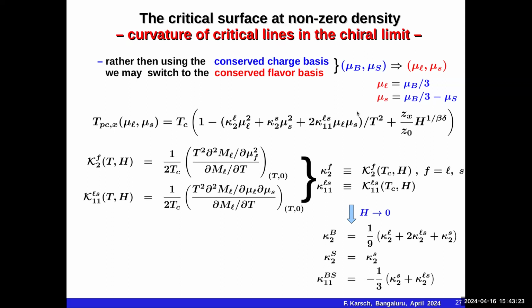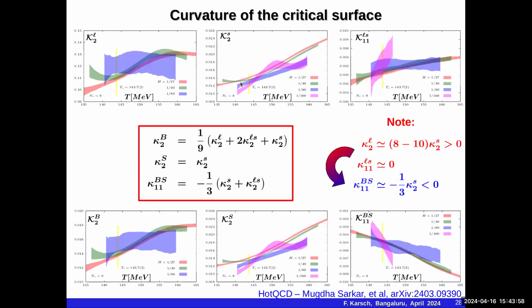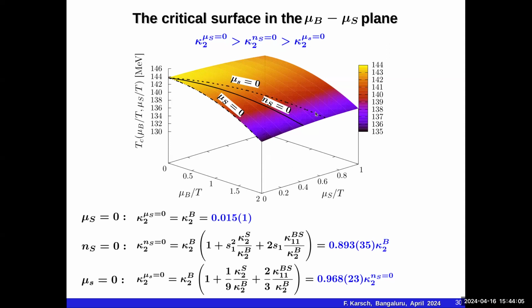Okay. And in theory, on the lattice, it is, for instance, convenient to set the light quark chemical potential equal to the strange quark chemical potential. That means one is effectively dealing with a particular combination of baryon and strangeness chemical potential. And that is sort of indicated here in this surface. When I set the strange flavor chemical potential to 0, then I'm effectively discussing a line in this plane which corresponds to certain non-vanishing baryon and strangeness chemical potentials.